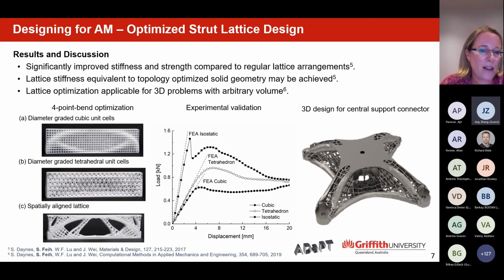So again, some very nice publications here that you can look up by Stephen Daines as the first author. So again, we actually predict all these things fairly well. The solutions are available. I want to point out that our minimum truss diameters here, we restricted to about 1 millimeter. So that is well within the manufacturing limit of the structure and the equipment, and the FE predictions are therefore in very good agreement.